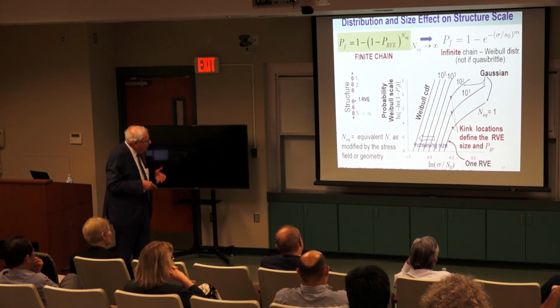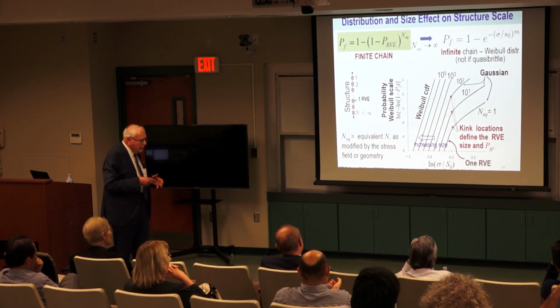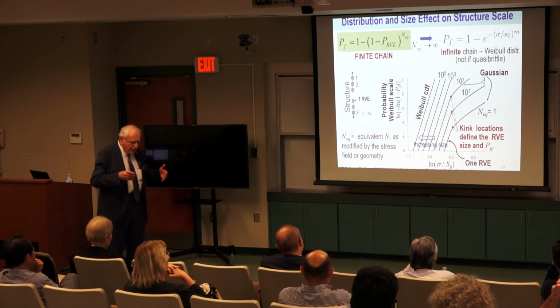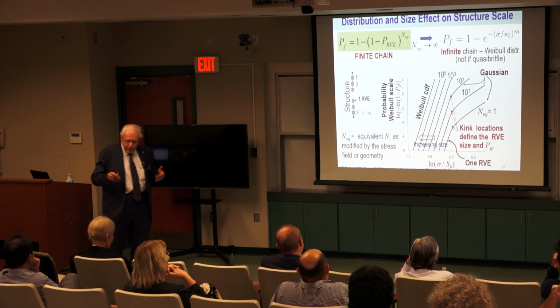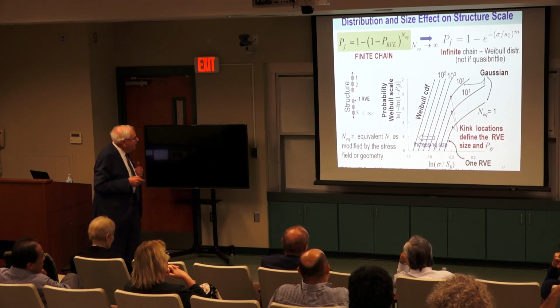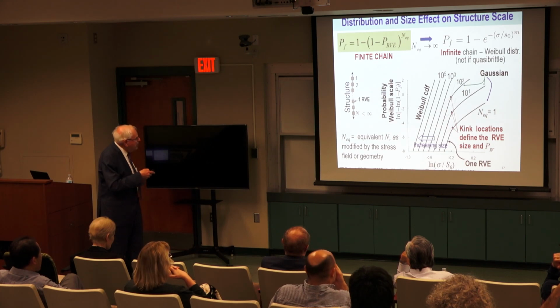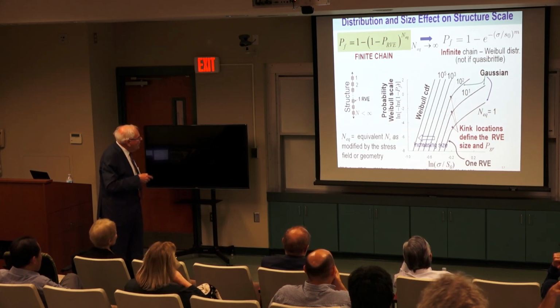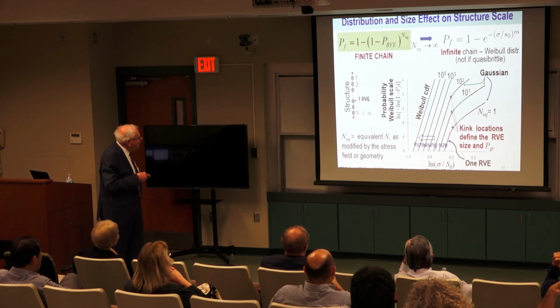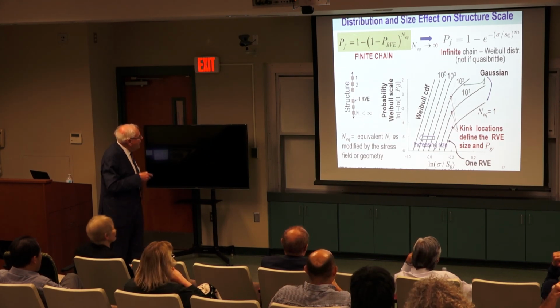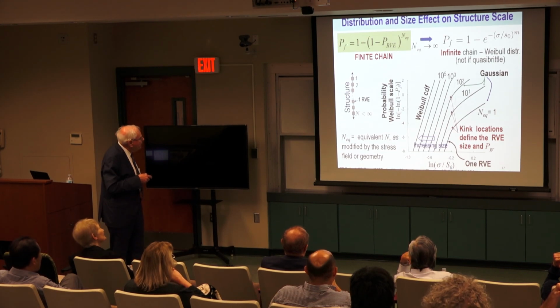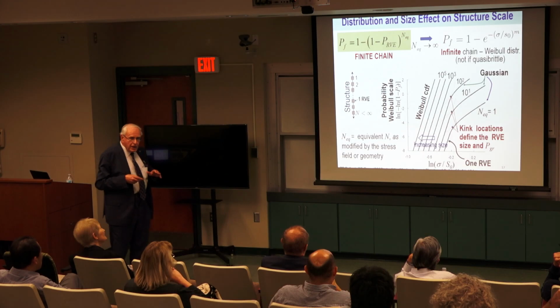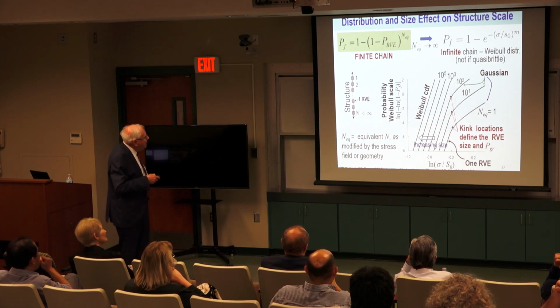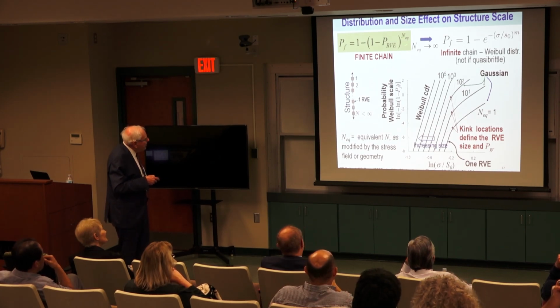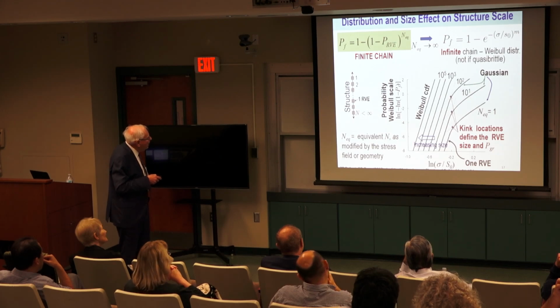And now we get it for one representative volume element, one curve, and when we consider structures which have so-called positive geometry, fail as soon as one RVE fails, not every structure does it, reinforced concrete not, then we need to calculate the failure probability of the structure as a whole. So we consider a chain, and basically what we are doing, 1 minus failure probability is survival probability. So imagine put it on one side. And that structure survives if all the representative volume elements survive, the joint probability. So, and these are identical. There is an exponent and the number, but it must be scaled by stress. I will not talk about this. This is the probability of 1 RVE.